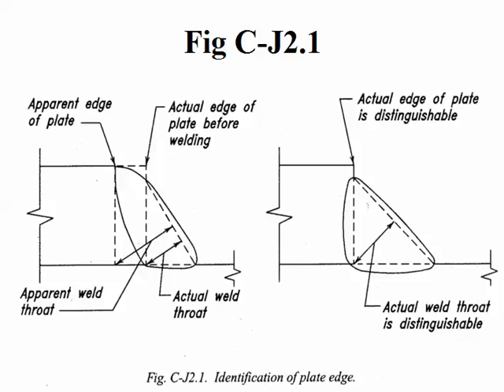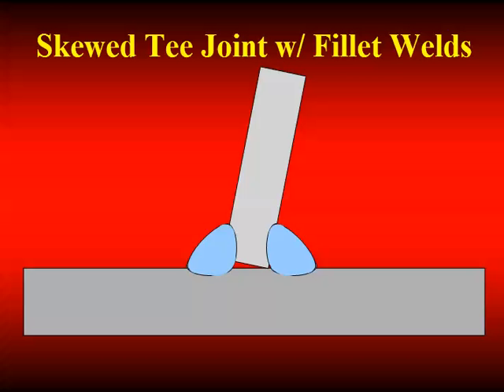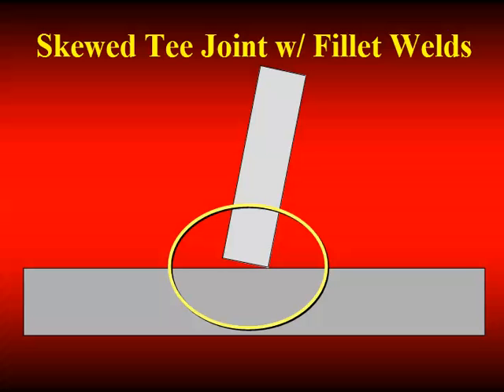Here's how the code, as AISC specification, deals with the issue in the commentary, which is pretty complete and explains the same thing. Fillet welds are not always in 90-degree joints. It could be in skewed joints. And we might call this a skewed T-joint. Some people call them skewed fillet welds. And you need to be careful when you get into skewed T-joints. Part of the reason is you need to look at how the preparation is applied to the end of that member. Now this is a 90-degree cut on the skewed member, so that the angle of the skew becomes the angle of this gap down in the root. There's nothing wrong with that, but we also need to realize that there are some implications behind that.